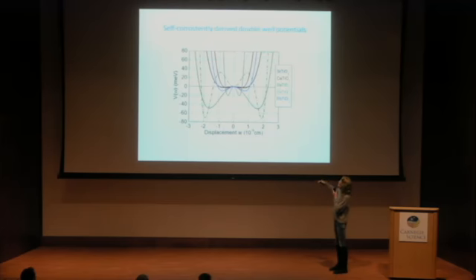Now we come to barium titanate. This is this broad potential, so very broad and very steep, and what came out from the calculation is that barium titanate can as well be described by this dashed green line here, because it has a first order transition. So this shows up in the fact that the dynamics can be modeled by 2 kinds of potential. But in the following, I just take this broad double well potential because it doesn't make a big difference for the dynamical properties. But you have to keep in mind that the transition in barium titanate is first order, and this is reflected in this dashed potential shown here.